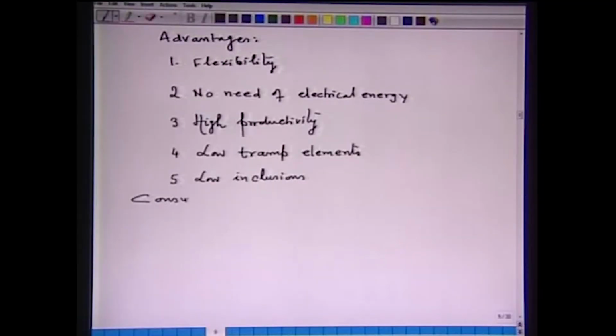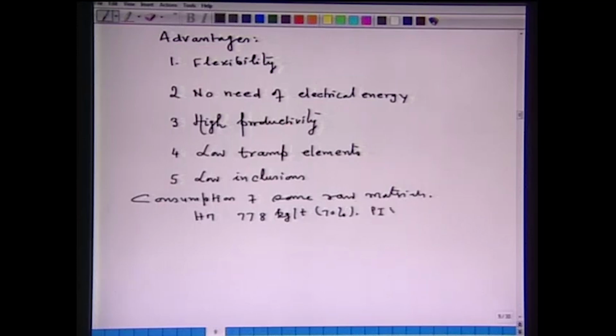Now, consumption of some raw materials. Hot metal 778 kilogram per ton, say around 70%. Then pig iron and scrap, that is around 330 kg per ton, which is say around 30%. Lime 45 kg per ton.